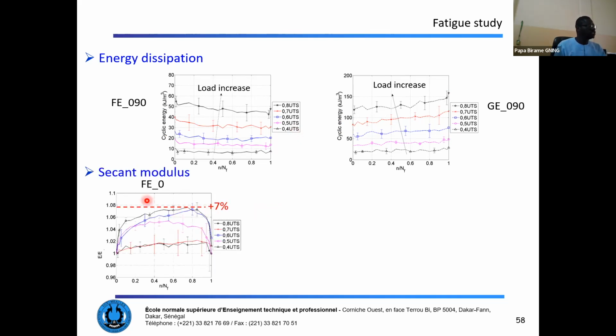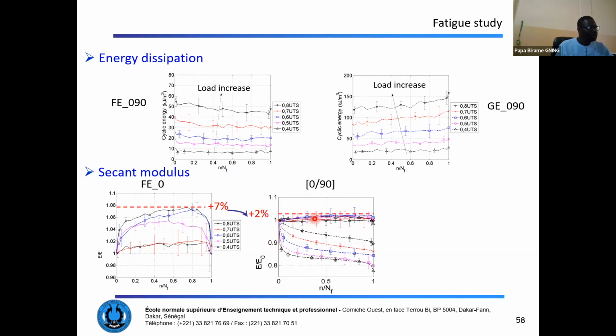So when you look at the secant modulus, which has the same trend as the dissipated energy, we can see that on the x-axis, you have the number of cycles divided by the total cycles. So when we are at 1, that means that the specimen has broken. And at 0, we are at the early loading. We can see that there is an increase of around 7% during the loading of the flax epoxy composites. When they are loaded at 0/90, we see that increase of the modulus.